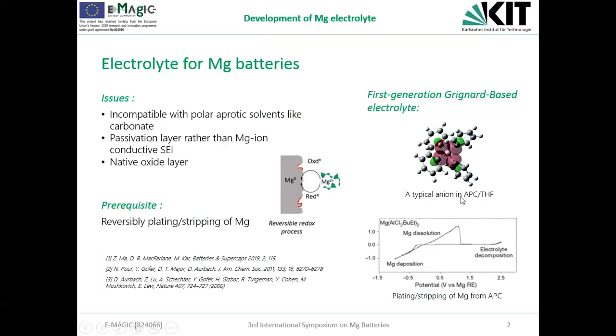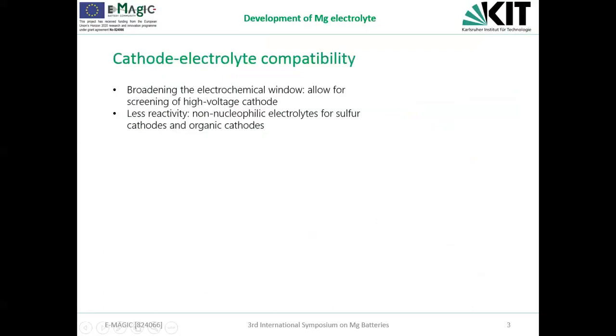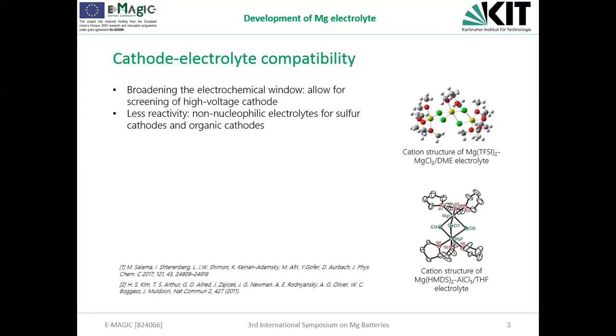And definitely with the addition of chlorine, we have an extended electrochemical window, and we also have better ionic conductivity. But the limit is still, in the APC case, we have a relatively narrow electrochemical window. And this limits us to further investigate the magnesium storage in a high voltage cathode. Also, the nucleophilic nature of the electrolytes makes it incompatible with the sulfur cathode and also with the organic cathode. And that's why several non-nucleophilic electrolytes have been developed.